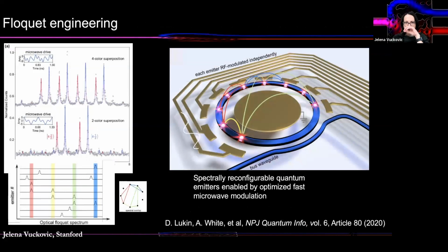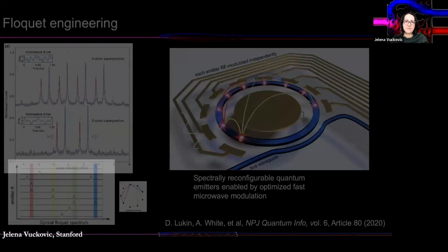And then experimentally, when we use some optimized microwave drive, we can completely change the spectrum of a silicon carbide color center. Instead of observing just two transitions that are the signature of silicon vacancy in silicon carbide, with two color superposition, we basically obtain these four peaks in the spectrum, or this different spectrum for optimized microwave drive with four colors. And by changing this optimized microwave drive on different quantum emitters, we can interface them onto each other, making them talk to each other, because these different harmonics in their Floquet spectra can start interacting with each other, which is something that we're very interested in because it offers another knob to turn in terms of building scalable systems.